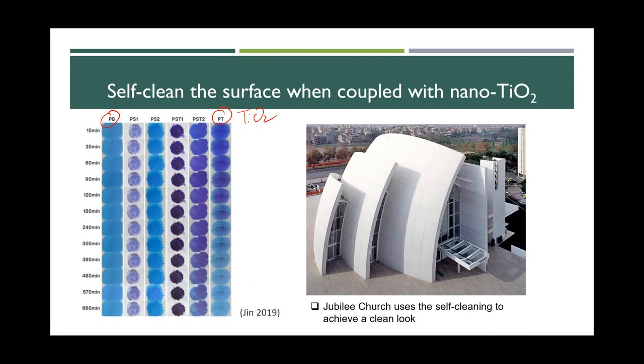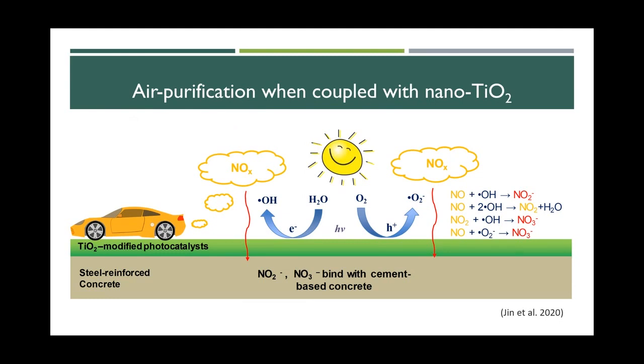So it has been applied to several infrastructures in Europe. The Jubilee Church uses this titanium dioxide to self-clean the surface and achieve a clean look all the time. And in addition to that, titanium dioxide can also break down NOx. NOx is a combination of nitrogen oxide and nitrogen dioxide. It's basically from your car. Once you have these pollutions, if you see a large area like Atlanta or Los Angeles, you have the fog, you cannot really see the buildings from far away, because of the NOx. And using titanium dioxide, you can break down NOx into nitrite and nitrate, and this can bind with cementitious components, and hence the air is purified.